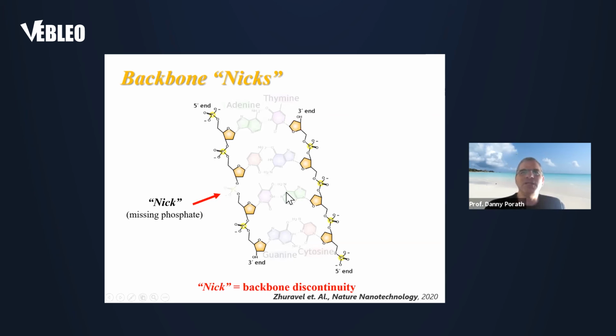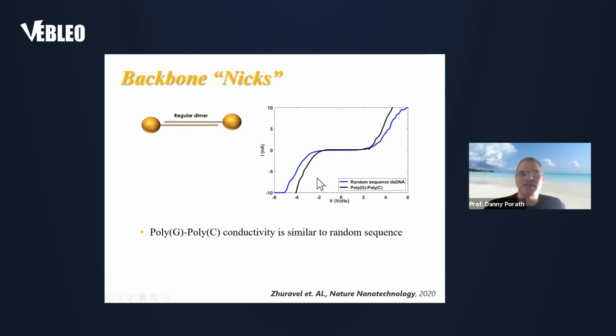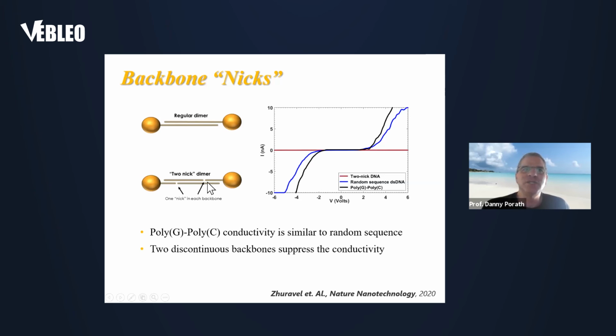So we went, and these are the results that I showed before. In a regular dimer, either homogeneous or non-homogeneous, we got a similar current. And when we check the DNA, here we made a nick in each one of the two strands because of the double helix, we wanted to cut both strands, and we did it with the nicks far apart. So there is about 50 nanometers between the two nicks, so they cannot form some kind of disruption to the structure. And then in this case, there was no current at all. So that was a strong hint.